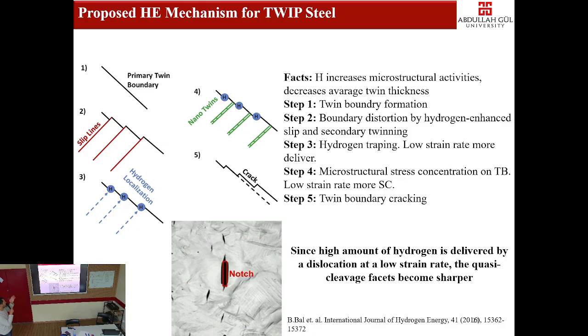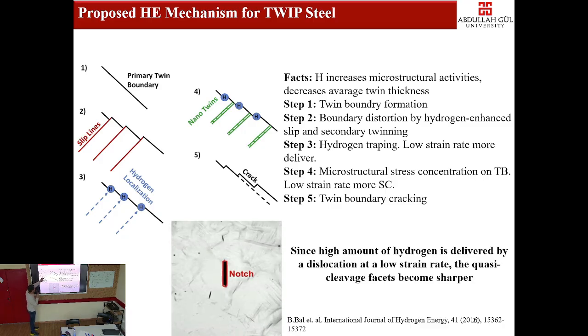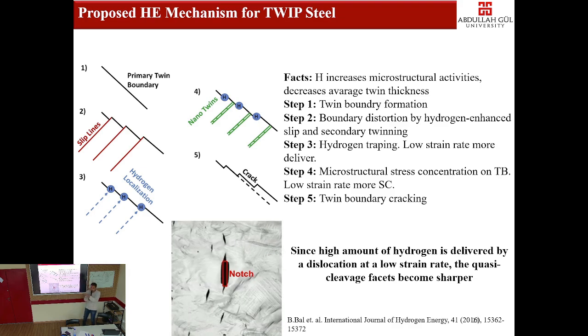We have firstly the primary twin boundary, then a nanotwin distorts the boundaries, and hydrogen slip lines distort the boundaries. Hydrogen localizes there. We have an additional nanotwin. Hydrogen always decreases the nanotwin size, but increases the microstructural features. Then we have a lot of stress here, and the crack propagates. This is twin boundary cracking, the mechanism due to hydrogen that we proposed in the literature. Of course, for a low strain rate, you provide much more time for dislocation-hydrogen interactions. That is why you can see more embrittlement.